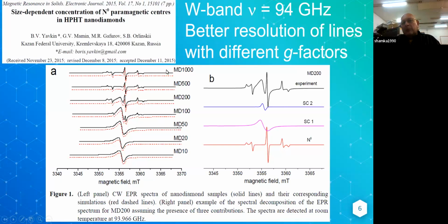Another work, EPR work, was done practically on the same set of samples provided by another company, but we are sure that it is practically the same samples. And this work was done at very high frequency. It's 94 gigahertz. For EPR, it's high frequency. And here you also can see, at high frequency, you have better resolution of the broad signal that appears in the center, and the P1 signal. They detected 3 types of signals: N0, which is P1, some broad line due to mechanical defects, and some unknown signal. And practically, they repeated the same results that were obtained earlier, independently, by this group.